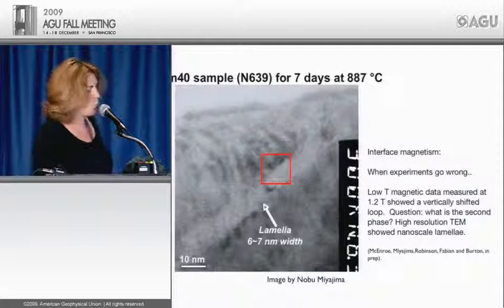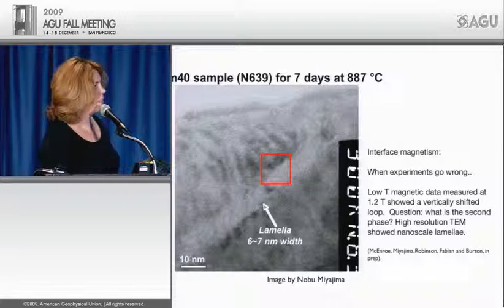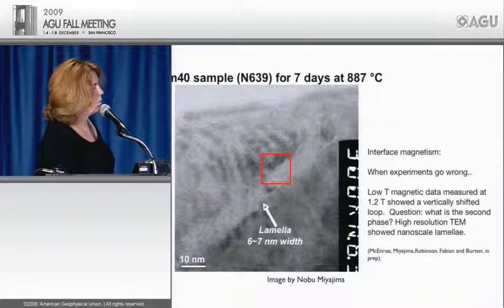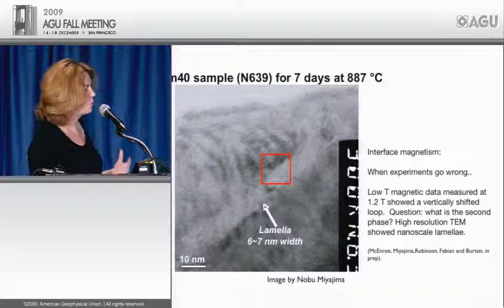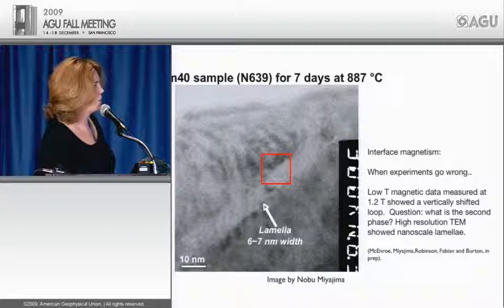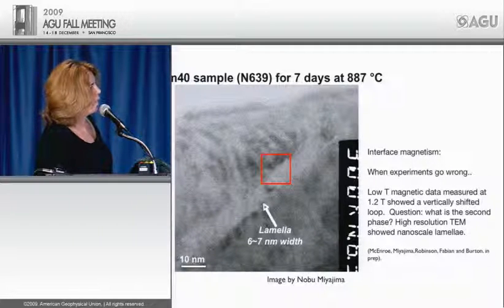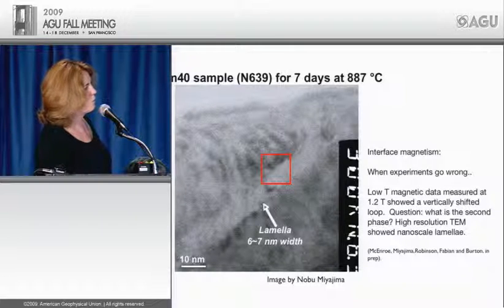Now, we're also doing a lot of work on synthetic samples. And this is an ilmenite 40 sample that actually was made quite a few years ago by Ben Burton. I've been analyzing all his samples left over from his thesis when he was originally studying the hematite-ilmenite solid solution. And this sample showed shifted hysteresis loop at very low temperature. And we were wondering what could be causing that. And so we went to the TEM.